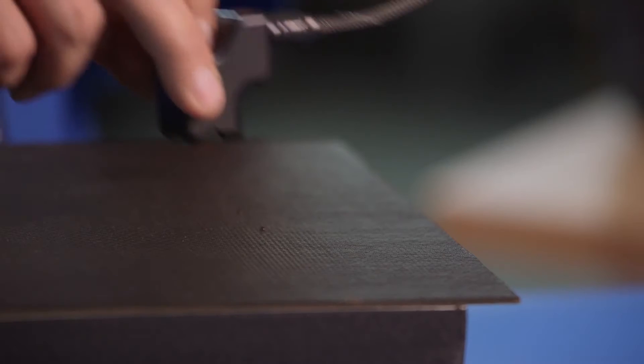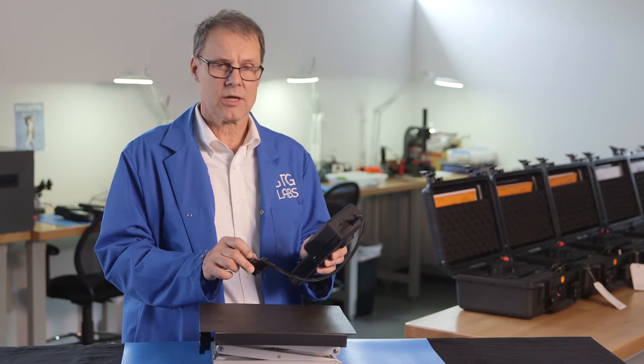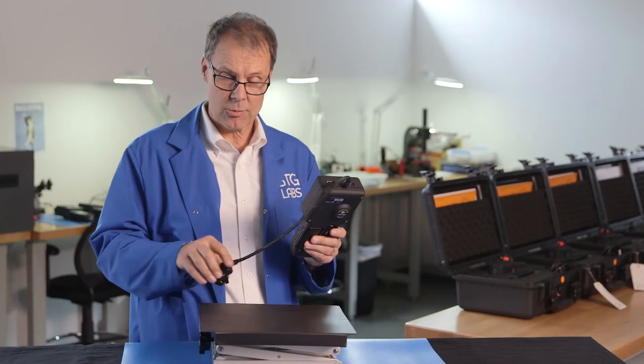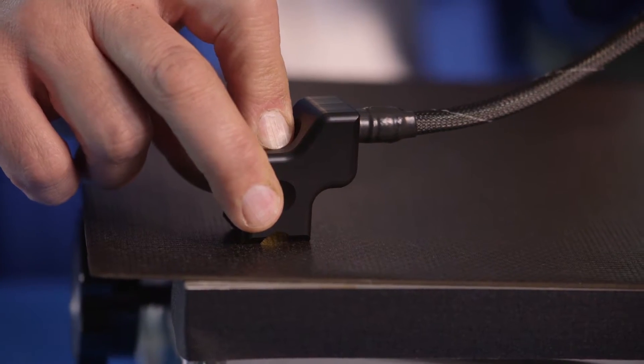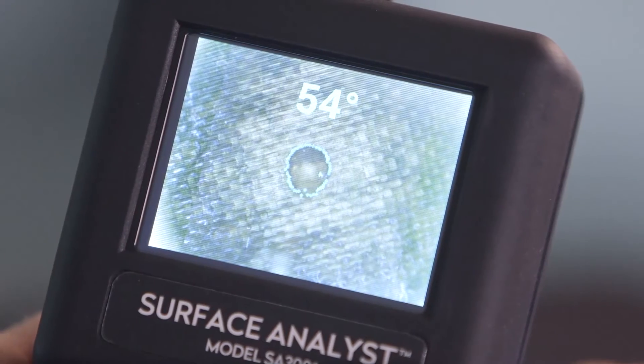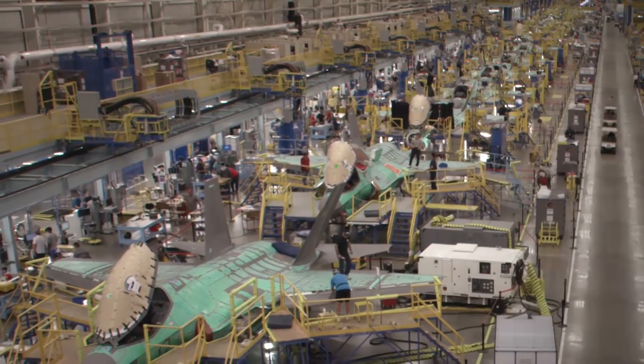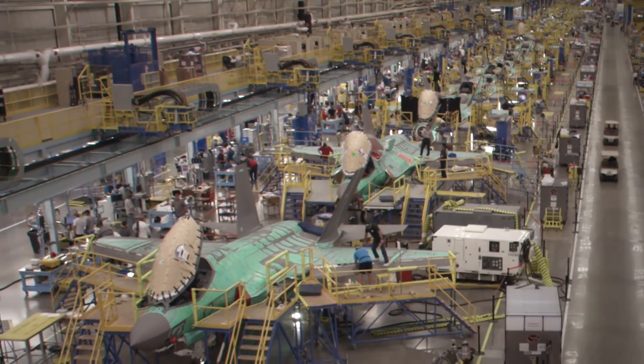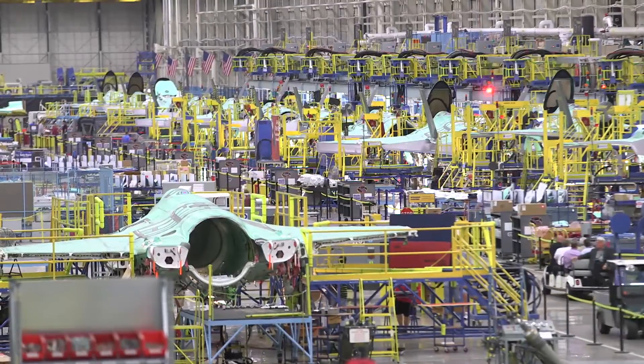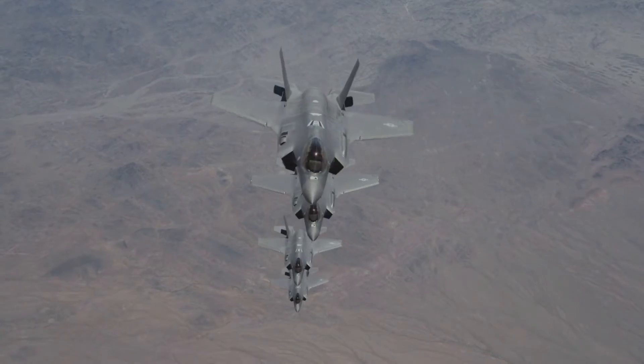But if I take a measurement on the part that hasn't been prepped, I put a little tiny drop of water down and establish an average contact angle of about 70 degrees on that surface. What that means is the water is really kind of beading up. Now if I take a measurement on the area that we've cleaned by simply wiping it with a solvent, I'm getting a contact angle on that drop of 54 degrees. The drop is spreading out more. That tells us if we put an adhesive on that surface, it would stick more strongly.